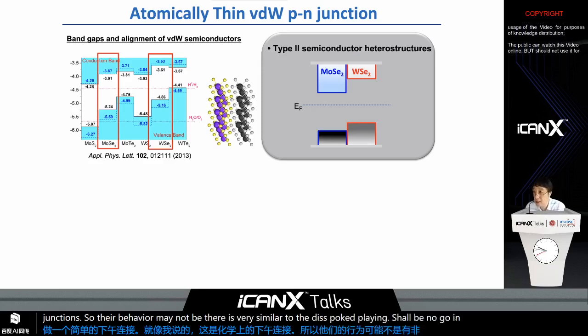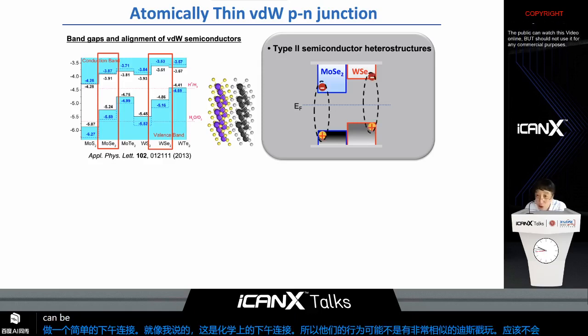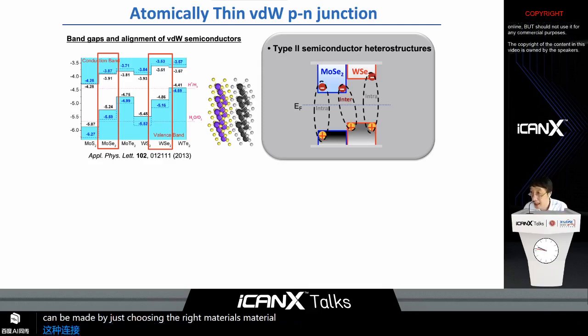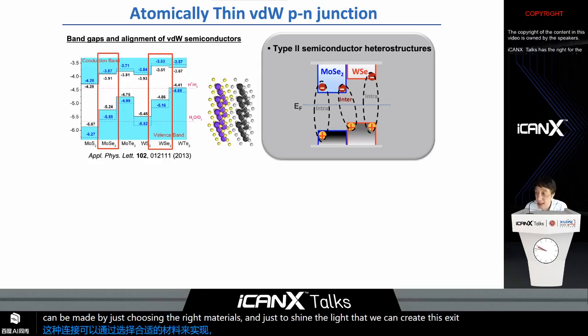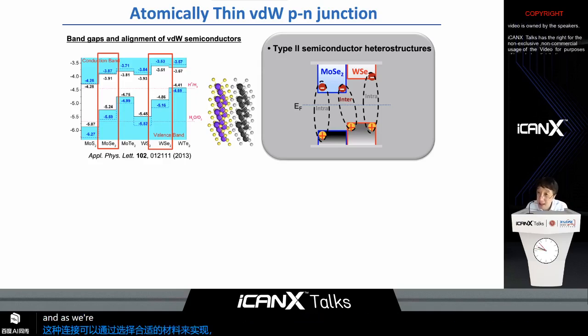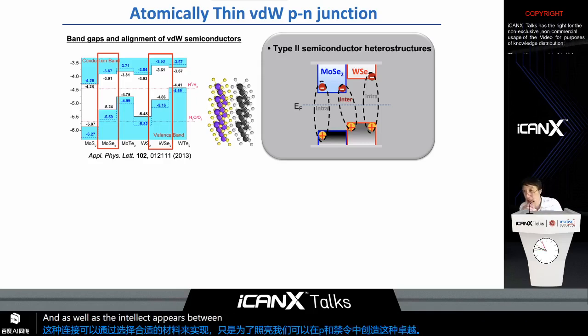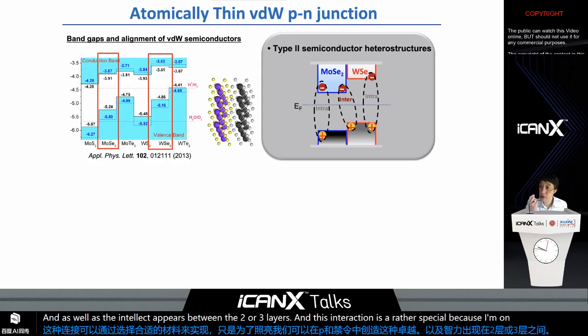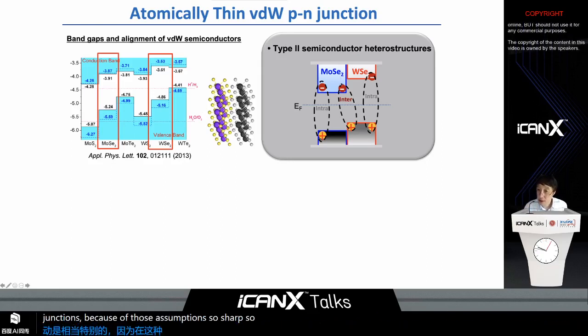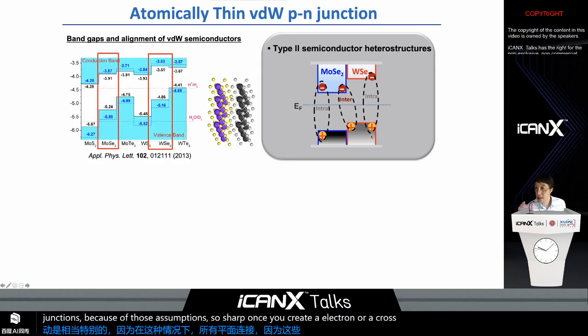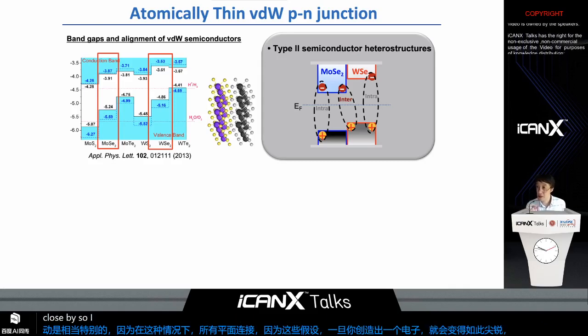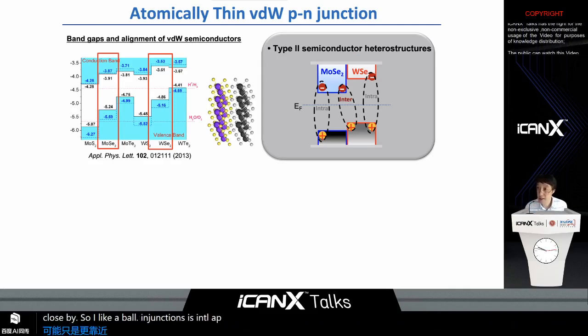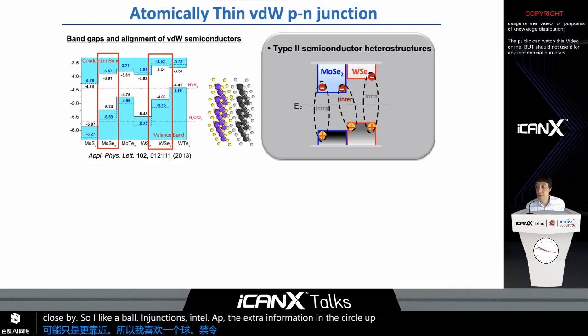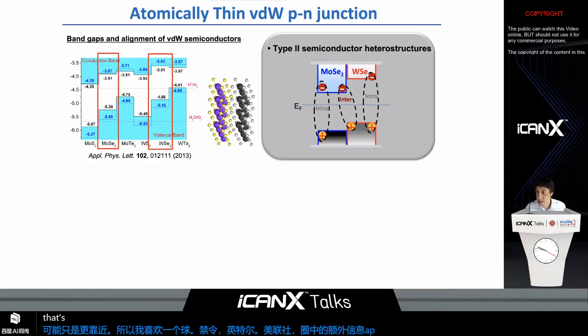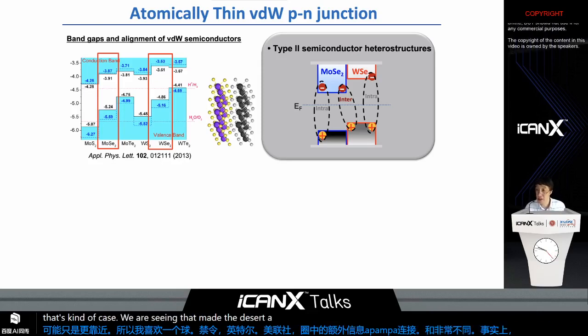Indeed, this type of p-n junction can be made by choosing the right materials and shining light, so that we can create excitons in the p and n layers, as well as the interlayer excitons that appear between the two atomic layers. And these interlayer excitons are rather special, unlike in bulk p-n junctions, because the junction is so sharp that once you create an electron and hole across it, they are situated very close by. So the interlayer exciton formation in this atomically thin p-n junction can be very different, and indeed that's the case we are seeing: the atomically thin p-n junction is distinguishably different from bulk.